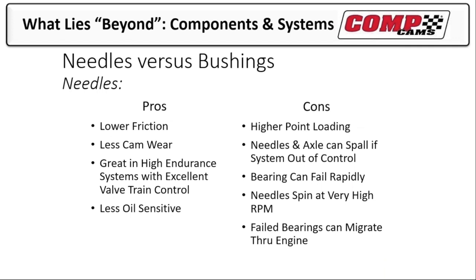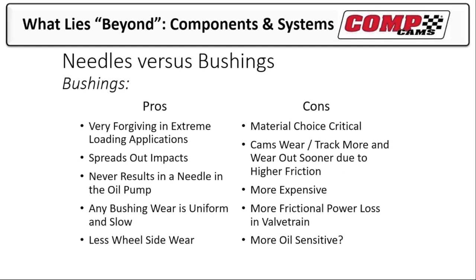Now you'll hear people go, well, should you run needles or bushings? Well, needles are really good because they're low friction, less wear on the camshaft, and great endurance. And they have very little oil sensitivity. The negative of it is it has high point loading. So if you're out of control and slamming together, you can get bad stuff like this, the needle and the axle can start spalling. The bearings can rapidly fail. And those needles are spinning at a really high RPM. And if you do fail a lifter, you've got all these little bits of needles that go all through your oil system and make a mess on your dry sump pump.